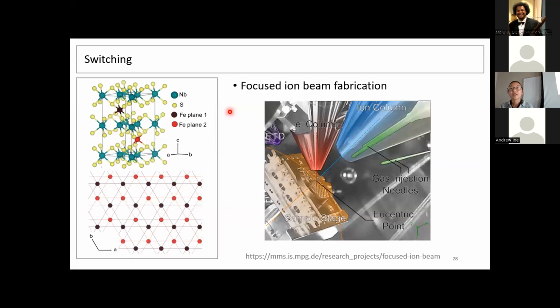Okay. And I do my measurements. I make devices using a focused ion beam. So this is a nice image that I took from the internet, so I gave some credit here. But basically, I'll be imaging my crystal using a scanning electron microscope. And at the same time, I'm shooting it with gallium ions, like a really focused beam of gallium ions, in order to cut very precise patterns into the crystal. And I'm also able to deposit specifically platinum. In principle, you can deposit a lot of things, but also with very high precision using this system.